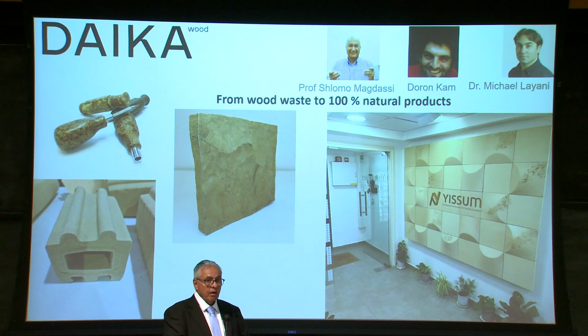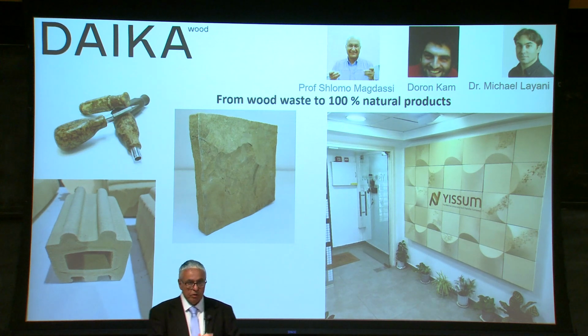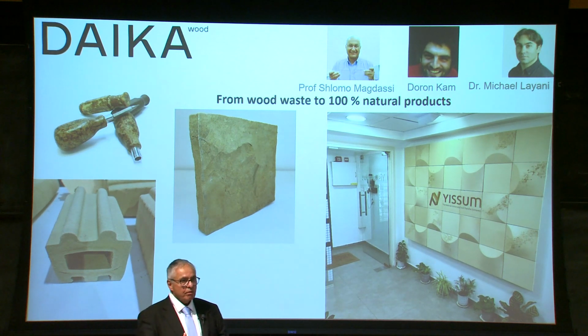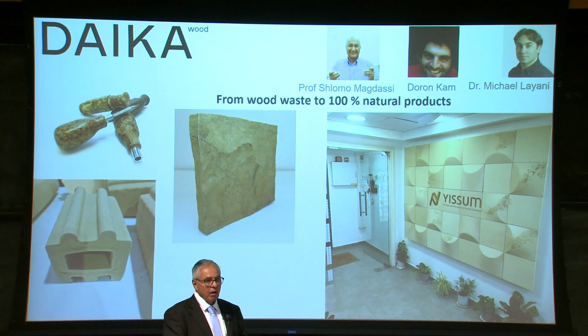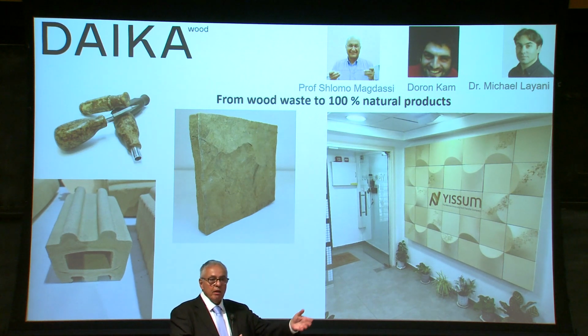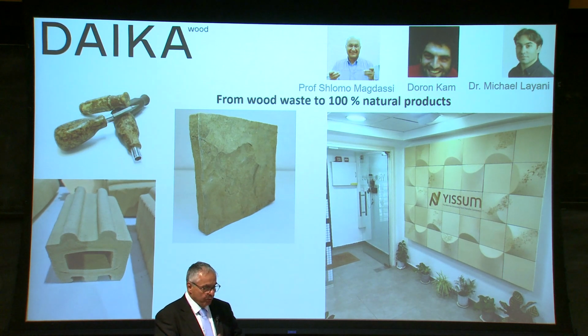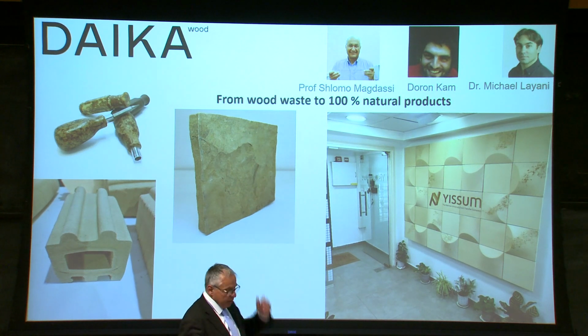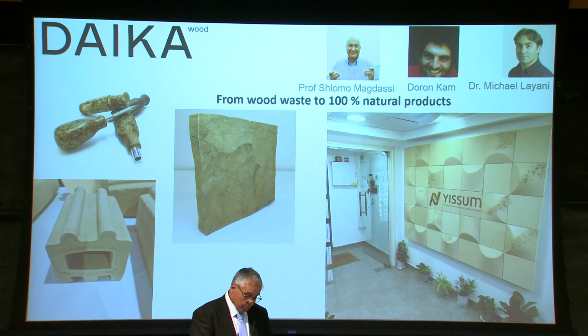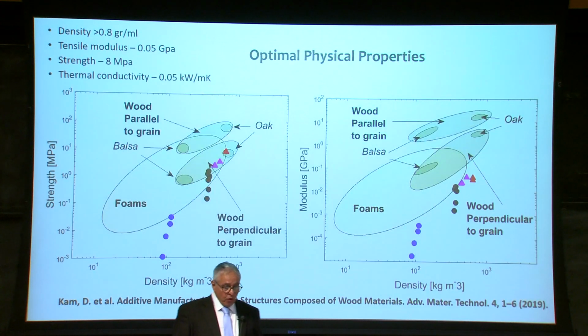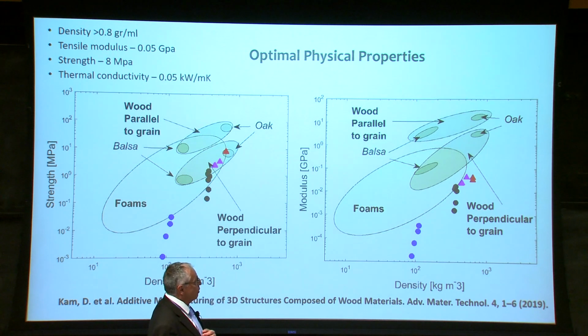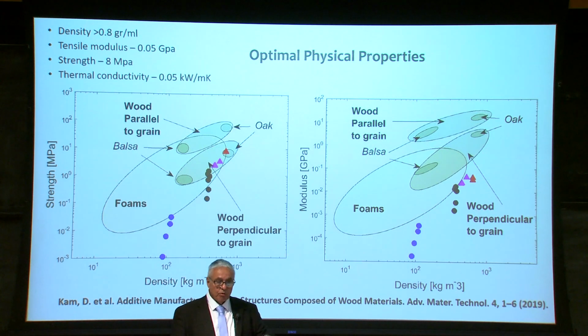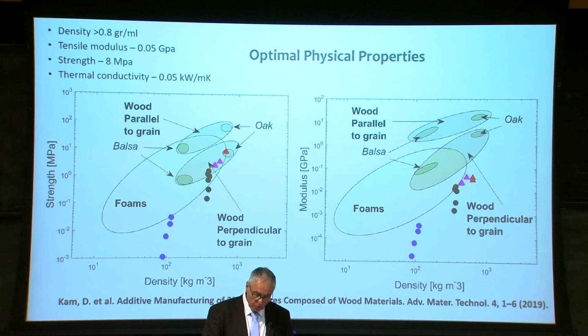We've been able to develop a very nice material, we call it Daika wood, which uses cellulose nanocrystals as the binding or gluing material of sawdust that is now collected by the municipality every Wednesday in Israel, crushed, and instead of going to the ground for landfilling, we can actually make a really beautiful material and products from that. And it's very strong. You can see here, we published it some time ago in Advanced Materials, that it performs similarly to the strength of oak. So it's quite a strong material.